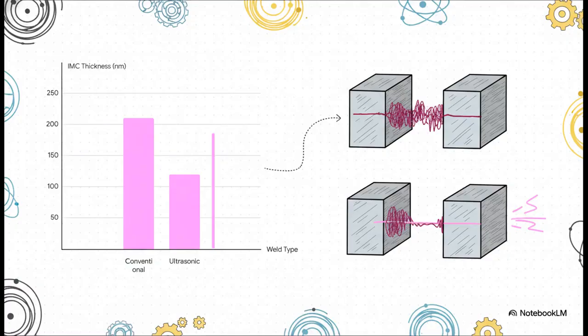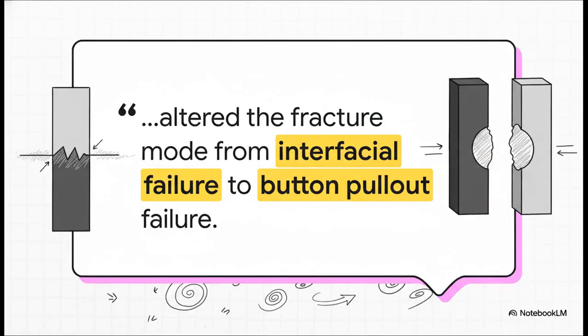In a typical weld between a type of aluminum and titanium, that brittle IMC layer was about 200 nanometers thick. But by adding those ultrasonic vibrations, they shrunk that weak layer all the way down to 120 nanometers. That's a massive reduction in the weak spot, which means you get a much, much stronger weld. So, what does this super sciencey quote actually mean?